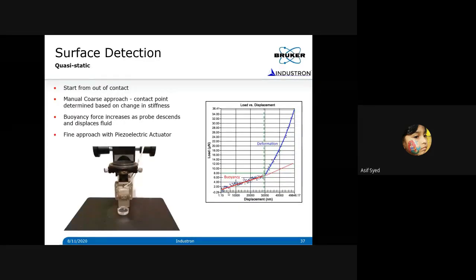So how you are making contact, how you are detecting it, there are two ways of doing it. In a quasi-static mode, as you bring the probe, it comes in contact with the water or the liquid that you have in a submerged condition, and then we can measure the change in buoyancy, and from the change of the slope, we can see where actually it is making contact. That's one way of doing it. I'm also going to present a force modulation technique where we can use the phase shift as you approach as a way of finding the surface of the sample. There are two approaches. I'm going to show that in the following slides.